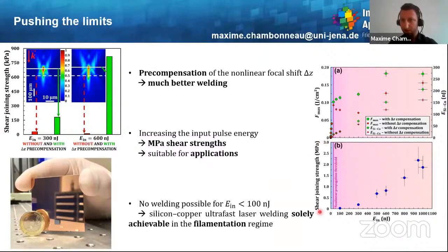Well, the results are essentially shown here on the right with those blue points, and one can see that it is possible to reach megapascal, like more than 2 megapascal shear joining strength with this strategy for around 1 microjoule input pulse energy. And this value of more than 2 megapascal is suitable for applications. Interestingly, one can note that there is no welding possible for input pulse energies below 100 nanojoules, meaning that silicon to copper ultrafast laser welding is solely achievable in the filamentation regime, which completely justifies our approach of measuring and precompensating the nonlinear focal shift.